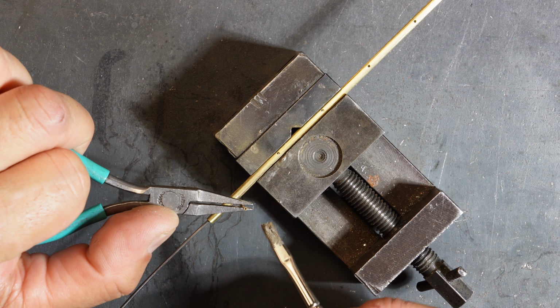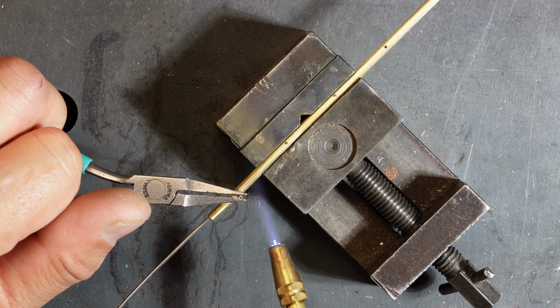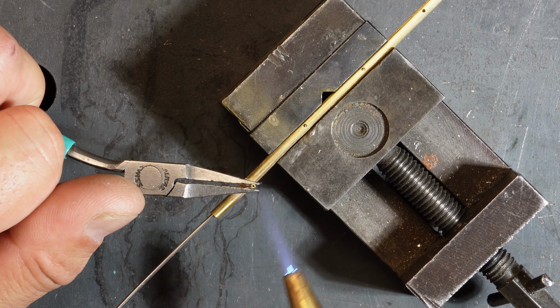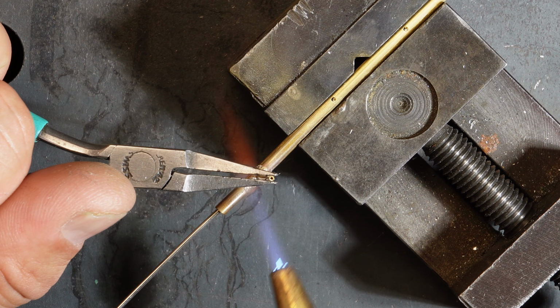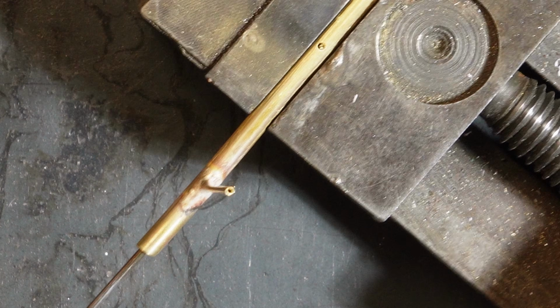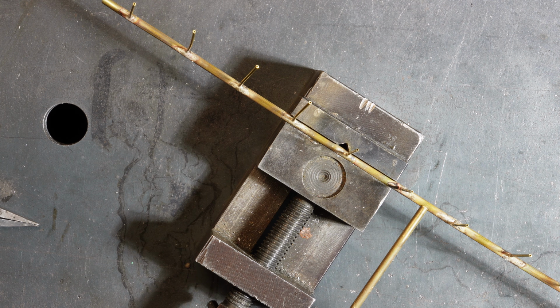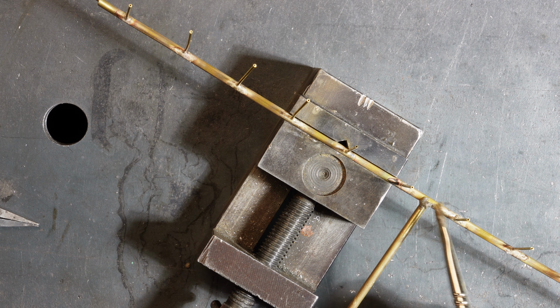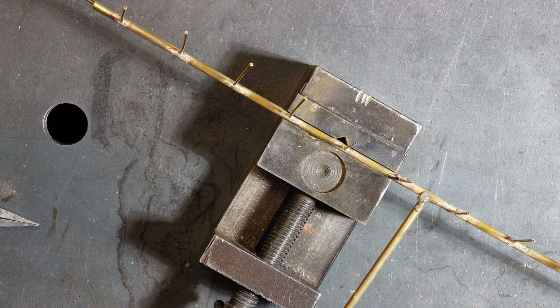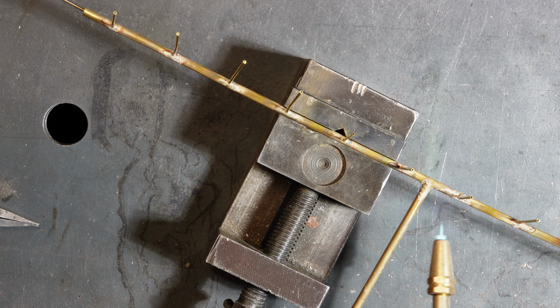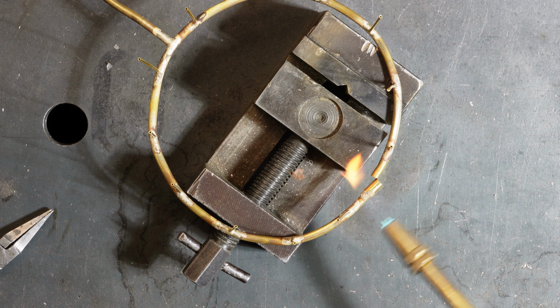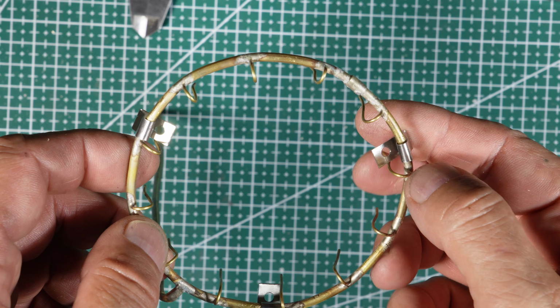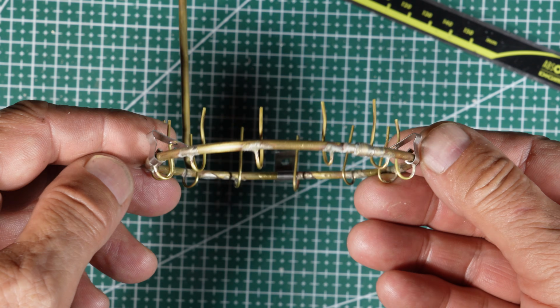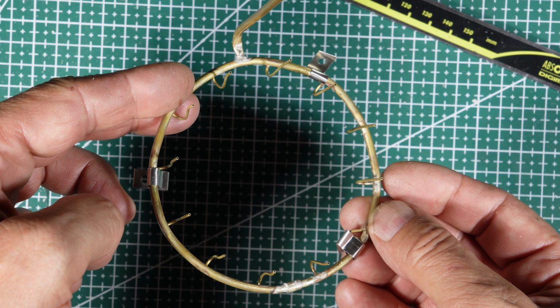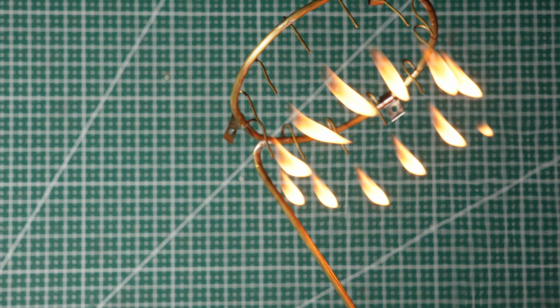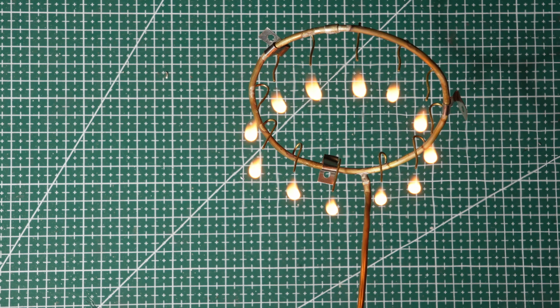For the fuel manifold, I switched to silver brazing using 60% silver filler rod and an oxy-fuel torch. To maintain alignment during brazing, I insert a steel rod inside the 3mm brass tube. Before bending the manifold, I anneal the brass tubing at approximately 400 to 600 degrees Celsius. This softens the material and greatly reduces the risk of cracking. Once the manifold is complete, I perform a gas flow test. All 12 outlets produce very similar flames, indicating good flow distribution throughout the system.